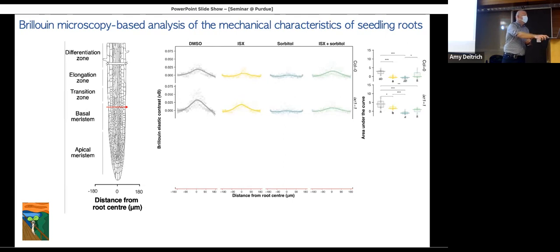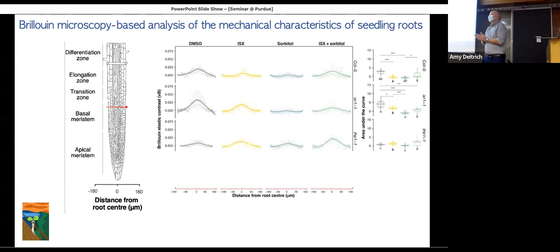Now, interestingly, when you take the TCOS1 loss of function, you see a qualitatively clearly different response. With respect to DMSO versus isoxaben, there isn't really a difference anymore, so it seems not to respond. When you look at the sorbitol, it's still responding like the wild type. And when you look at the combined treatment, it's again still responding. Interestingly, or possibly even more so, when you have the overactivated version, there is no effect with the isoxaben treatment, but it seems to affect the response when you have the combined treatment.